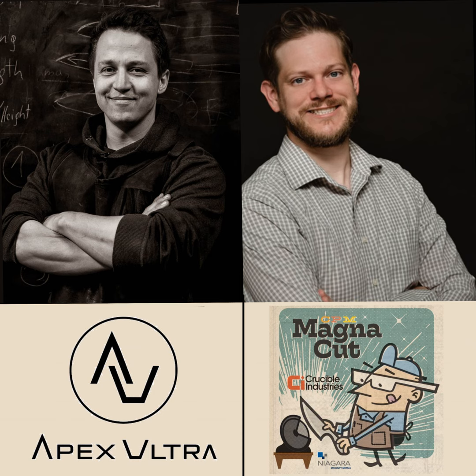And that's the best test. If you etch it, it's like a cloudy area that doesn't etch correctly. Absolutely. It even looks really good on forged blades sometimes. If you leave it close to the spine, it looks like you have a laminate, like a Sanmai or Gomai. But it usually etches bright, whereas, at least if you have a dark etching steel anyways, then you can see it on the outside. And even if you forge a blade in 20-30 minutes, there's going to be decarburization on there. And if you take 2 hours to forge a blade, then there's definitely going to be a lot of decarb on the surface of the steel. So, same thing, I always recommend grind a little deeper, and then you will see if you have full hardness.